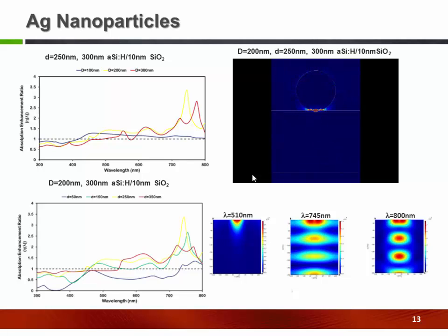Actually, the incoming light causes the free electrons to resonate with the incoming light, but that's a very theoretical condition, because it depends on the size of the particle, how the free electrons inside the metallic material are going to resonate with the incoming light. This resonance is re-radiated in the forward direction, and as you see, it's still visible here. This resonance causes the concentration of the light to increase only locally, depending on the position of the metallic particle with respect to the absorber layer.